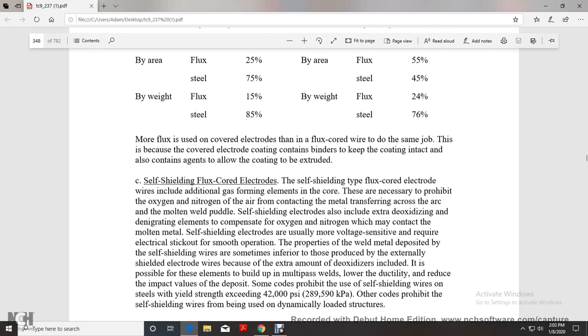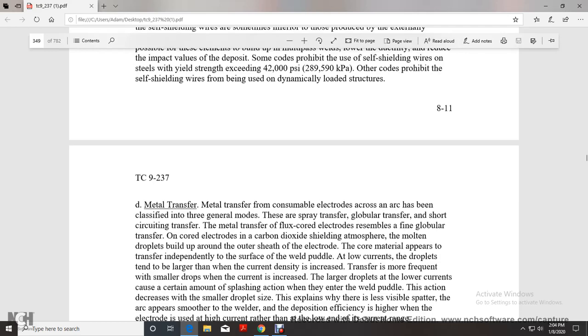They require a specific electrode stick-out for smoother operation. The properties of the weld metal deposit with self-shielding wires are sometimes inferior to those produced with externally shielded electrode wires, because of the extra amount of deoxidizers included, with the possibility of elements building up with multiple passes, lower ductility, and reduced impact values of the deposit. Some codes prohibit self-shielding wires on steel with a yield strength over 42,000 pounds. Other codes prohibit self-shielding wires being used on dynamically loaded structures.